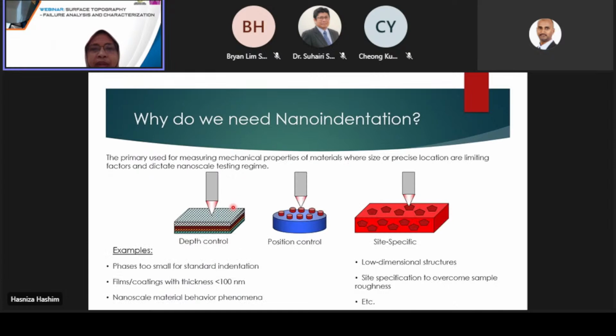So why do we need the nano indentation? The primary objective of using the nano indentation is to measure the mechanical properties of material where the size or precise location are limiting factors. As an example, if you have very thin layers and you want to know the hardness and modulus of the top layer, we need an instrument that can control the depth of penetration of a thin film. We must take care when indenting a thin film to avoid also testing the properties of underlying layers.